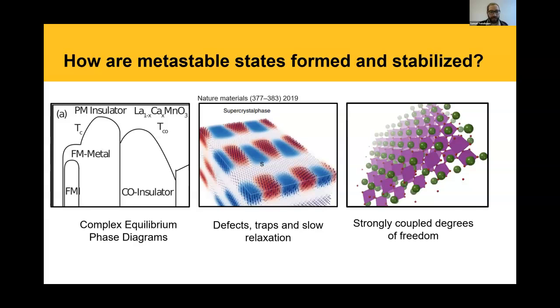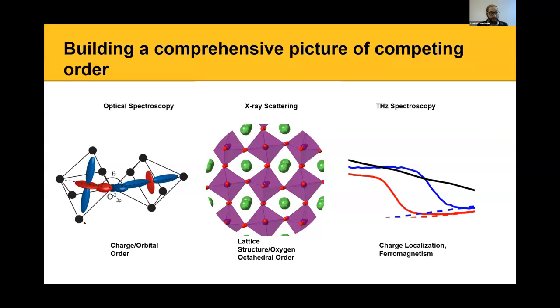So experimentally, how do we tackle these kinds of problems? In order to build a comprehensive picture of competing order, ideally we would like to probe all of these orders simultaneously in the time domain as they evolve. In this talk, I'm going to talk about 3 kinds of probes: optical spectroscopy, X-ray scattering, and terahertz spectroscopy, which are going to probe our charge and orbital order, the alternating manganese oxidation states in particular. For the lattice structure, we're sensitive to a monoclinic to orthorhombic transition. And terahertz spectroscopy is going to probe charge localization, which in the manganites is intrinsically related to ferromagnetism. You can think of the terahertz response as probing how far along you are towards the ferromagnetic state. You can think of the optical response as what the local electronic structure looks like. And you can think of the X-ray scattering as probing what the long-range lattice structure and the long-range charge ordering look like.